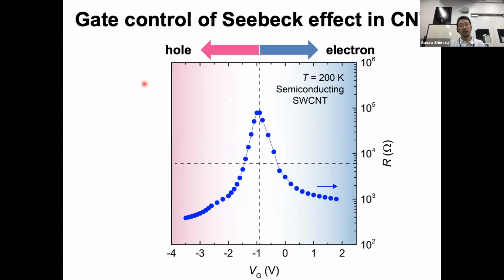Here we show some experimental data. This graph shows the gate voltage dependence of the resistance of the carbon nanotube thin film. When we increase the gate voltage, the resistance of the carbon nanotube increases, shows a maximum and starts to decrease, like this. So this means that when we apply negative gate voltage, the carriers in the carbon nanotube thin film are holes. And when we apply positive gate bias, the carriers are electrons. And here, this point is the charge neutral point at which the Fermi energy or chemical potential is located just at the middle of the conduction band edge and valence band edge.